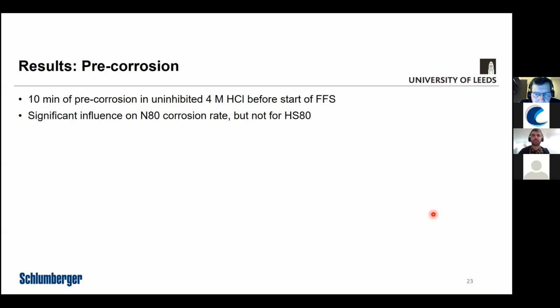So the experiments that I've shown you so far were all completed on a polished sample, a controllable surface finish, with no layers present on that surface, which is great for experimental control, but obviously is not necessarily what would be seen in reality in the field. So what we did was introduce a pre-corrosion period. We exposed the carbon steel to uninhibited hydrochloric acid for a 10-minute period. That allowed the carbon steel coupon to corrode. It influenced the surface that essentially would be exposed to the inhibitor once the flow of inhibitor starts in that system.